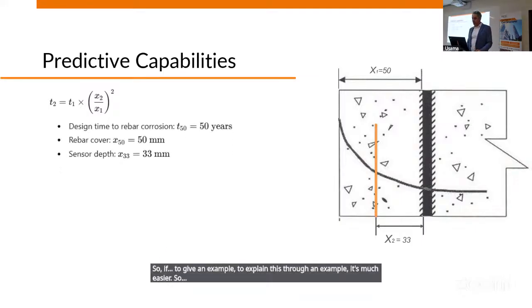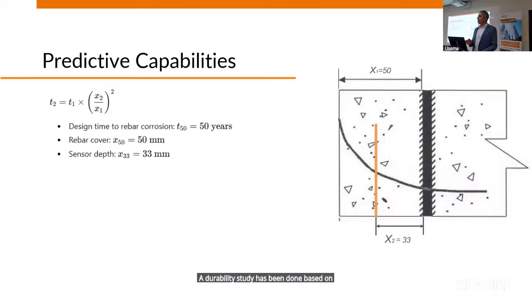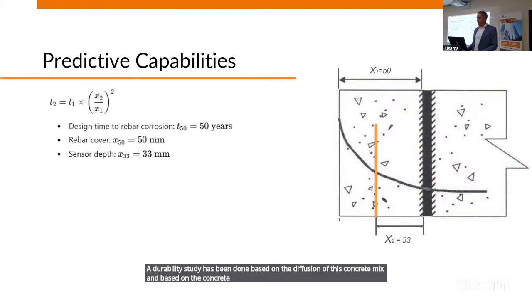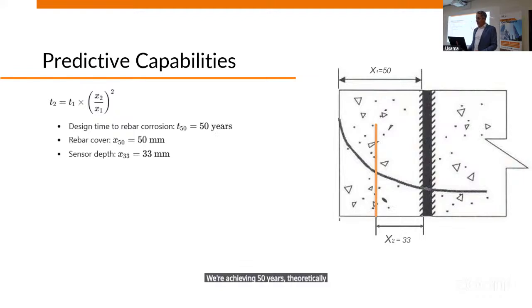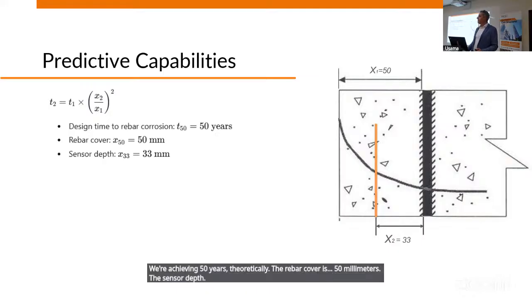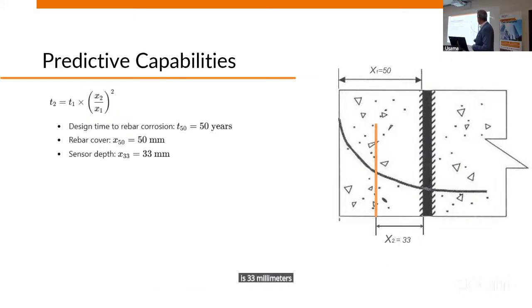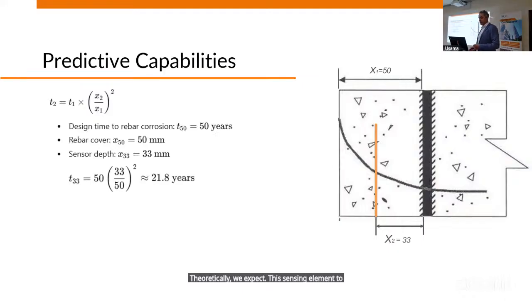So let's assume we have a structure that has been designed for a 50-year service life. A durability study has been done based on the diffusion of this concrete mix, and based on the concrete cover, we're achieving 50 years theoretically. The rebar cover is 50 millimeters. The top sensor is 33 millimeters. So cover 50, sensor at 33 millimeters. Theoretically, we expect this sensing element to trigger after 21 years within the service life of the structure.